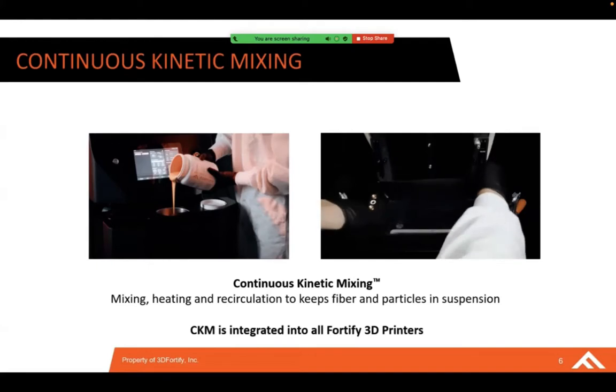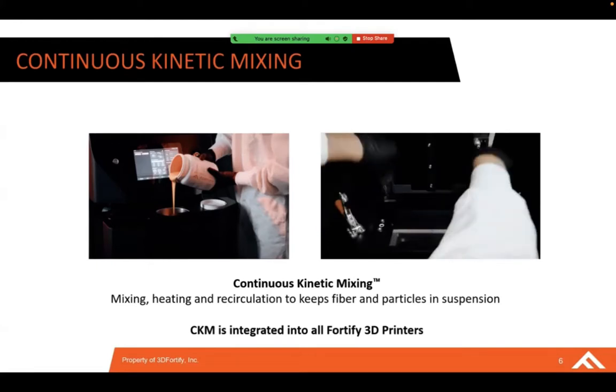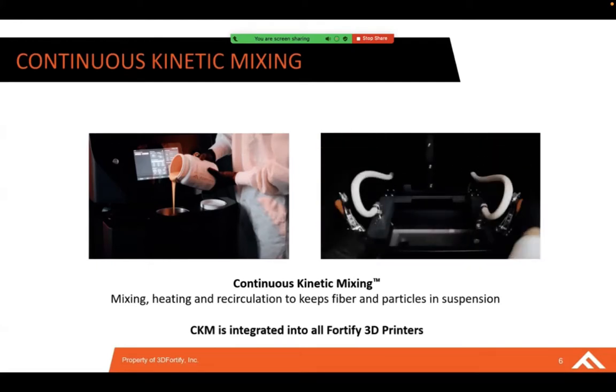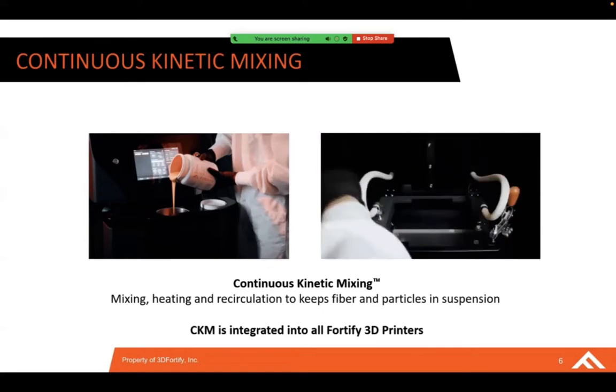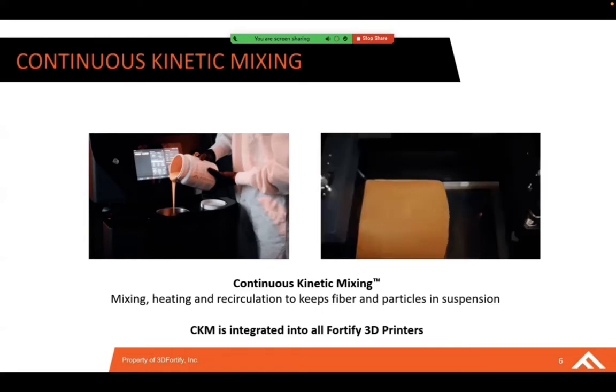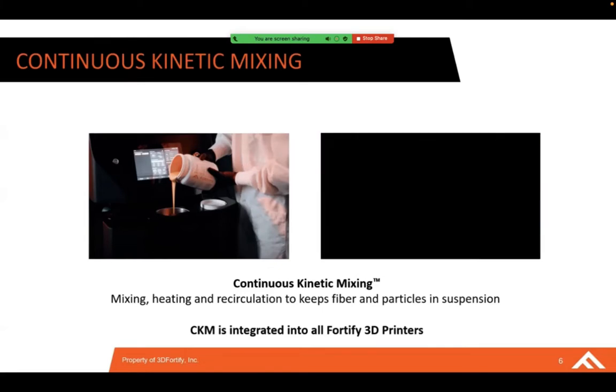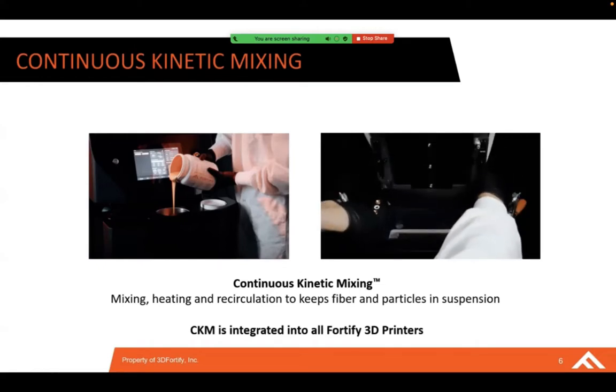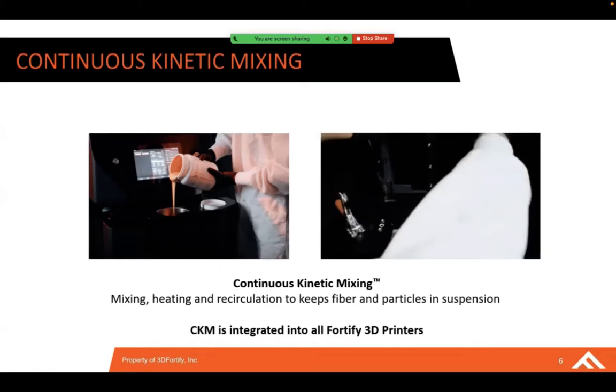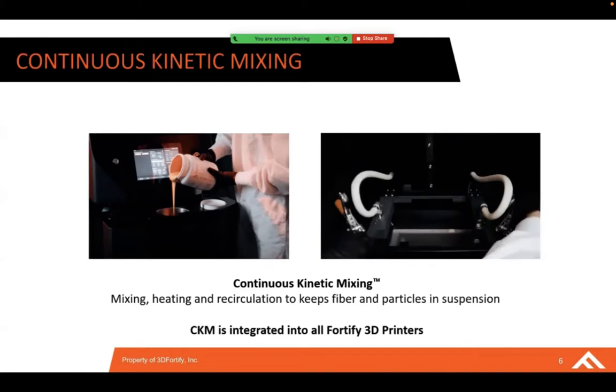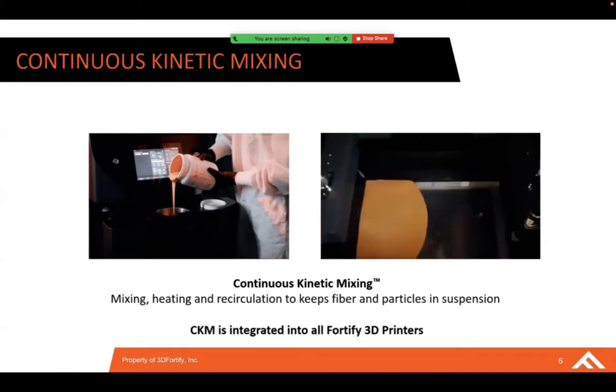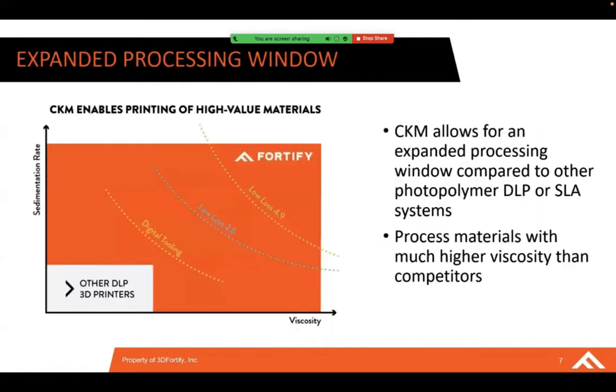By both heating and mixing, we're able to take advantage of viscosity reduction introduced via heat, while also managing the homogeneity of the heterogeneous material system through simultaneous mixing. So that means mixing and heating and recirculation keep fibers and particles in suspension. And this is integrated into all of the Flux series printers. With CKM, we're able to expand our processing windows into areas where other DLP systems cannot compete.